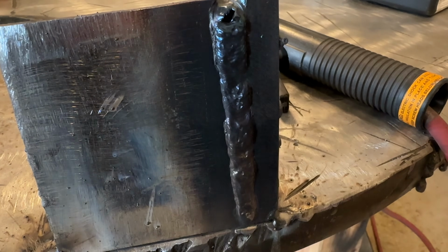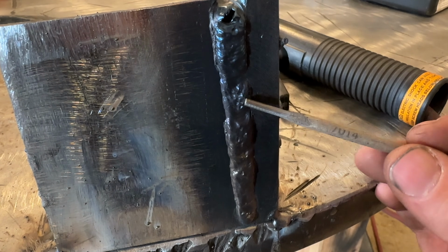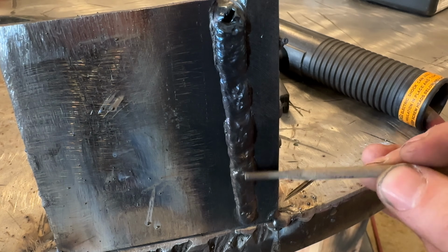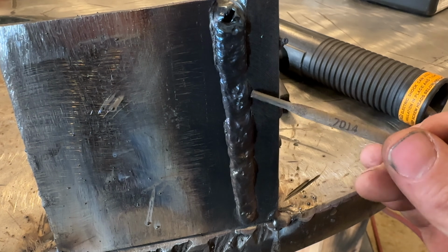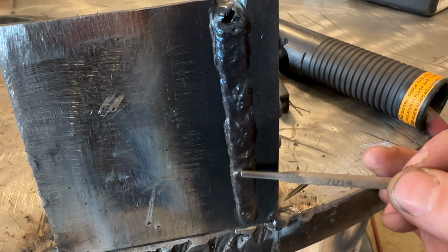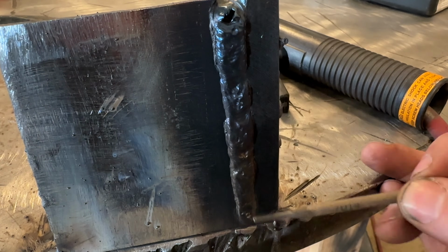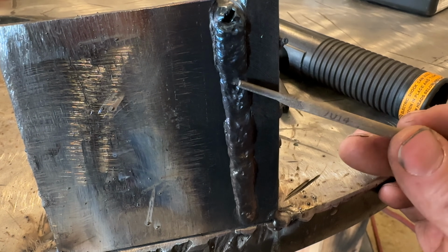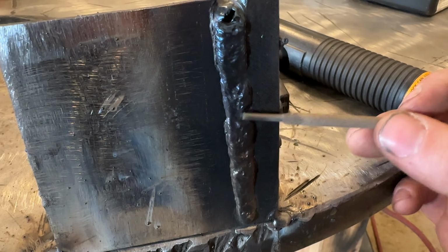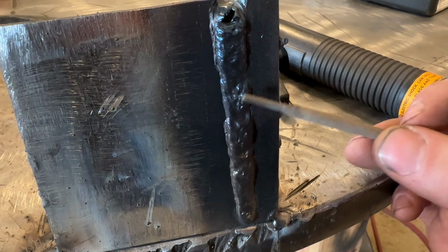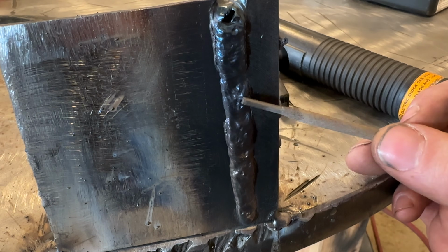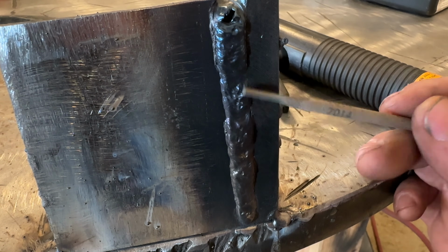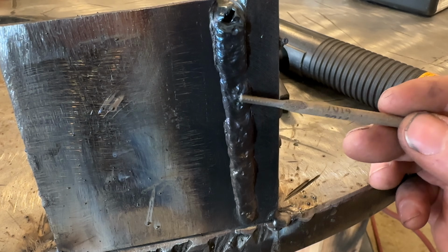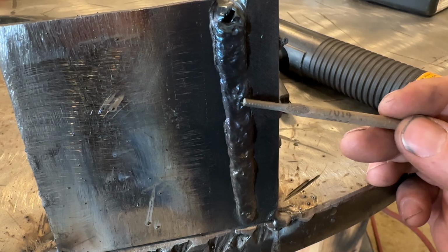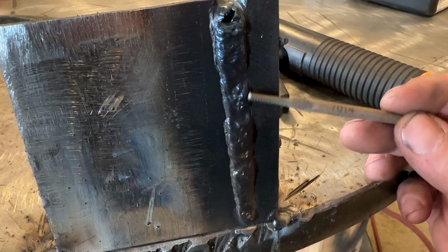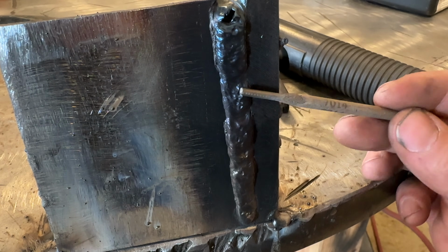So right away, a lot of interesting things here. This is not porosity, or at least it's not subsurface porosity. It has what appears to be bubbles right on the surface. And this almost looks more like flux core wire, self-shielded flux core wire. You get this when your stick out, your contact tip to work distance, is wrong. If it's too close, the molten puddle freezes too fast with self-shielded wire, and you end up getting this.